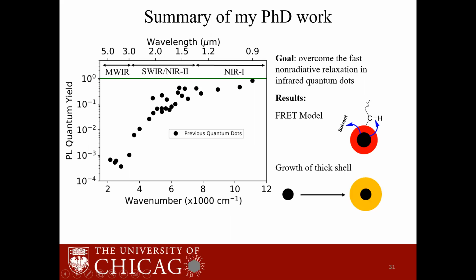And we have found some universal strategies for growing a thick shell around mercury-based quantum dots. And by growing this shell, we have gotten a record quantum yield of 2% at 5 microns and 60% at 1.7 microns. So this 2% is extremely low, and there is still a big room for improvement. So after 6 years, where with Philip, the next PhD student, if we can just extend this to 100%, then we will get thermal cameras which are sensitive at room temperature and will have a lot of commercial applications.